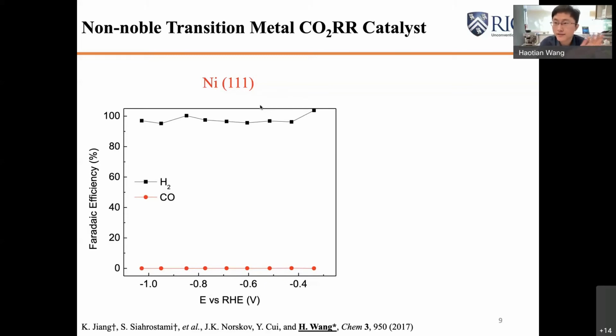But at that time, when I started my group, we didn't trust these theories. We just wanted to say, hey, why don't we try it? Why don't we use our experiment to see what's really happening? So we started with the nickel metal surface. We tested them in the CO2 reduction conditions. As you can see, almost 100% of the electrons go to hydrogen, and nearly no electrons go to the CO molecules. So that actually reflects the past theories are correct.